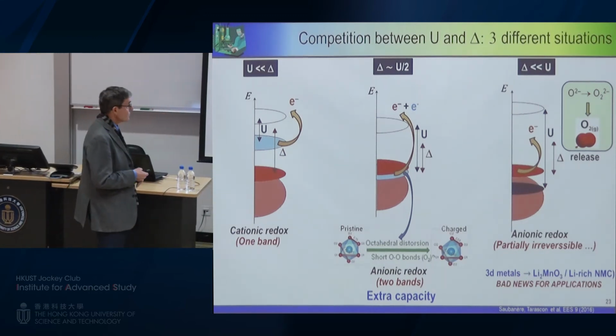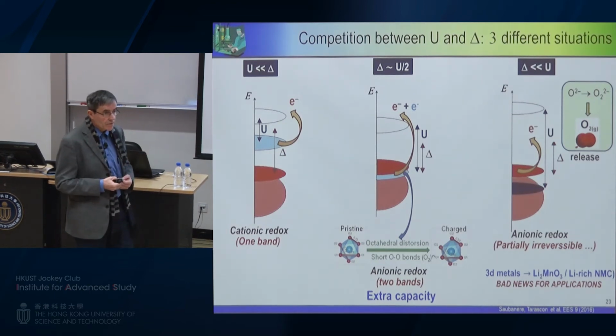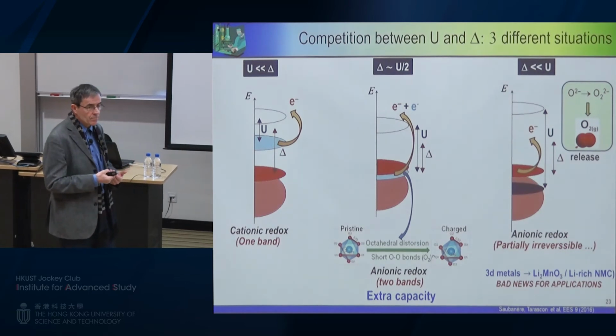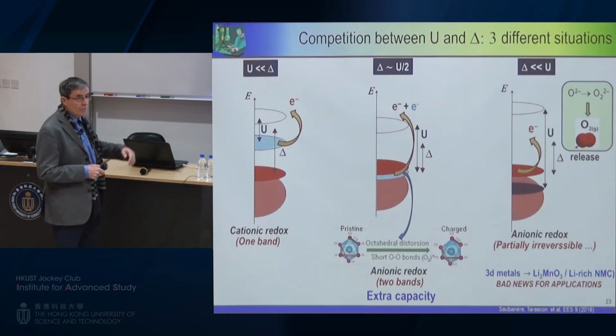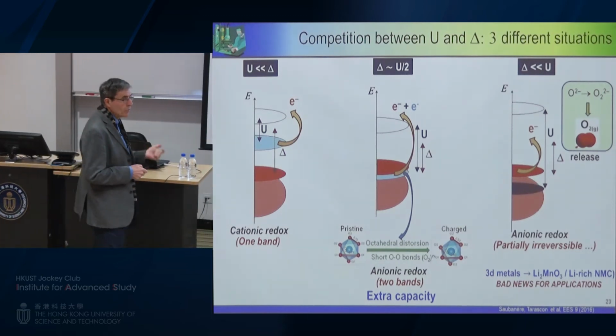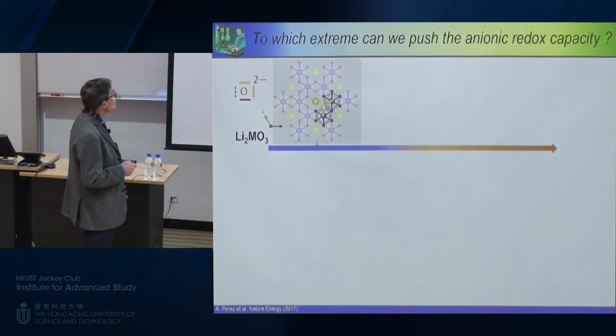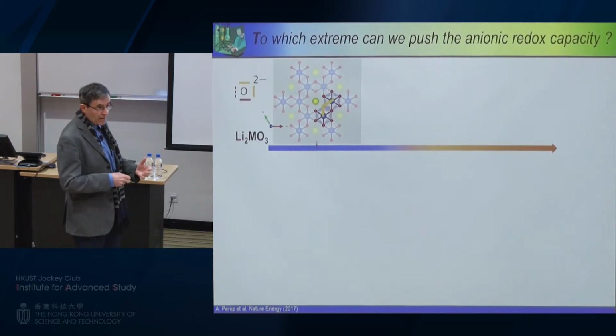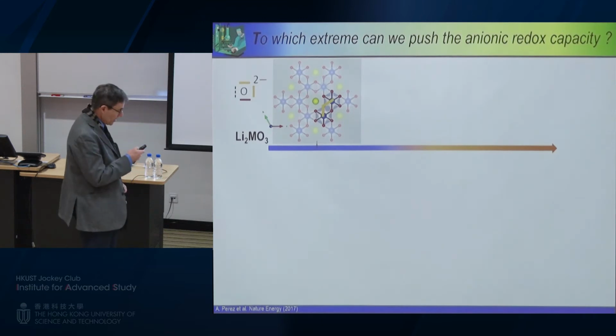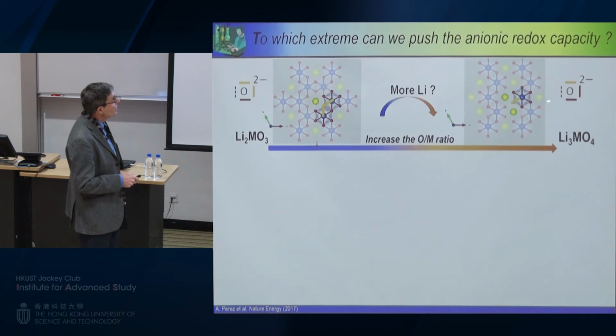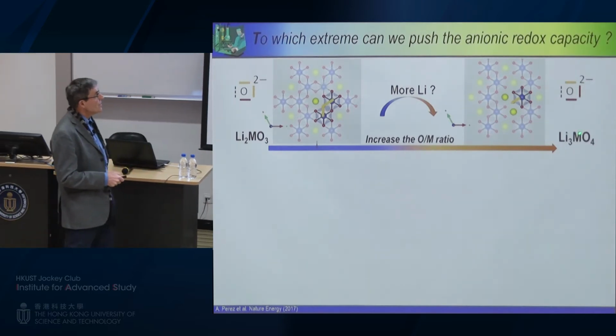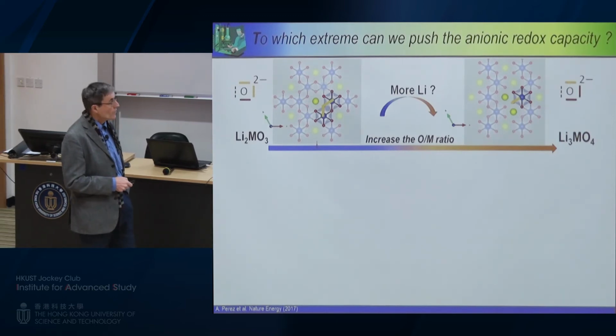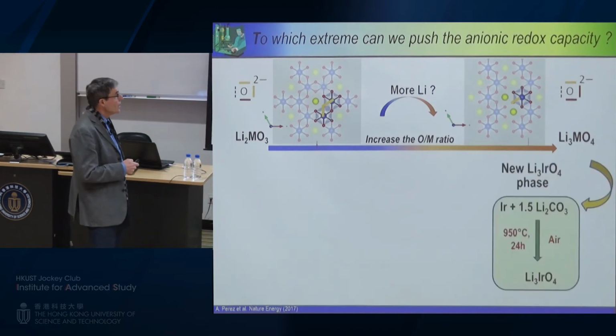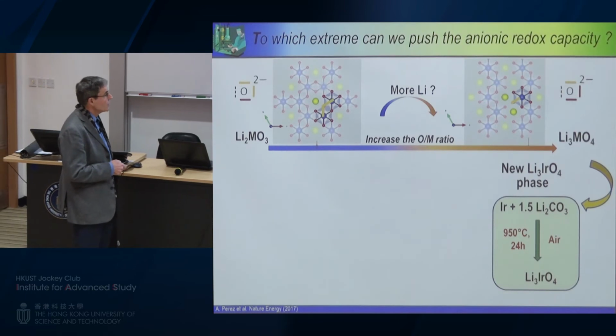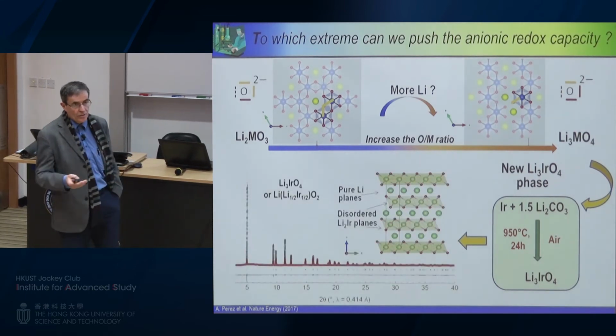So now, having this, of course, you can nearly, by yourself, tell me which direction I should go if I want to increase the capacity using anionic redox. Remember, I told you that you have oxygen with 3 doublets. I was able, by moving to Li2MnO3, in this case, as you can see here, to remove one. And if I want more capacity, let's get more non-bonding oxygen. So I need to design a structure in which I will have nearly a single involved 2p state and 2p non-bonding. And of course, if you want to design this compound, you need to synthesize the phase Li3MO4. This phase did not exist, and we were able to synthesize and prepare the material Li3IrO4, as clearly indicated here. And you can see that we indeed obtain a layered structure and so on.